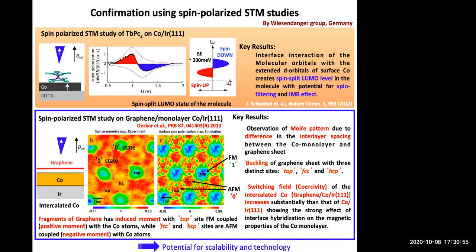But the main thing that is required, as I see, is strong hybridization. A priori it's very difficult to ascertain, but you can talk about classes of molecules. For example, the class of all heterocyclic molecules I would say are showing it, because they hybridize strongly with the surface. And this hybridization is governed by the molecular symmetry because they are planar aromatic. You have pi orbitals, pi bands, which couple strongly with, for example, the pz orbitals or p bands, or the d bands of the transition metal surface.